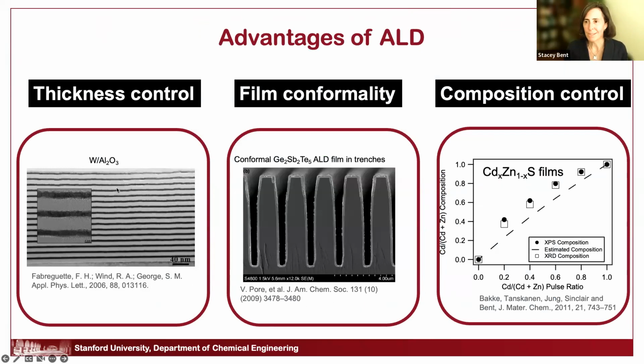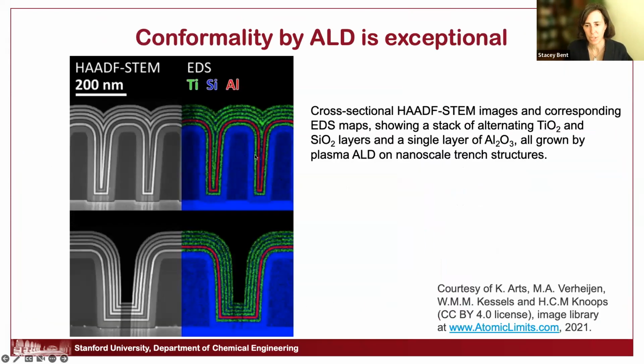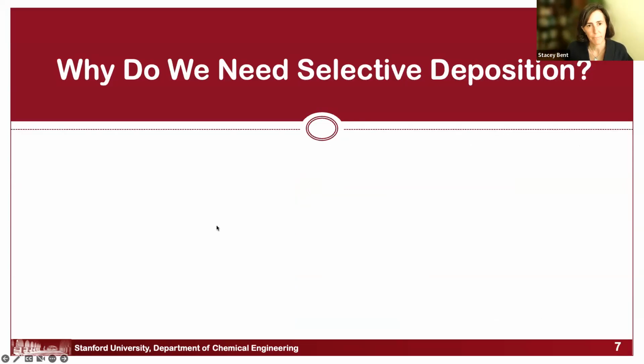The thickness control is exceptional because you just dial in how many cycles to get to a certain thickness. It's especially renowned and important in modern device fabrication because of its conformality. And this is an image which I think demonstrates it really nicely. It's exceptional, the conformality that one can achieve by this process of ALD. So this is just looking at a stack of alternating TiO2 and SiO2 layers in this nanoscale trench structures. And you can just see the beautiful reproducibility of the thickness as well as the conformality in this process.